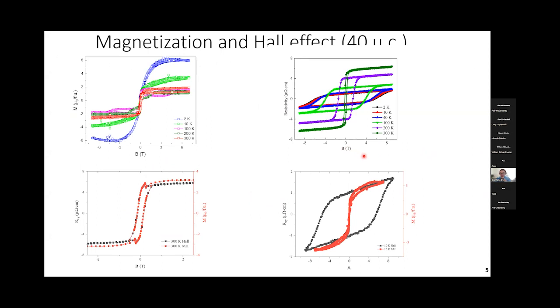So what is interesting in the film is the magnetic structure. When comparing with the single crystal, it implies a possible new order other than the ferromagnetic order, as in the single crystal. We use 2 ways to probe the magnetic structure. One is the magnetization loop, and the other is the anomalous Hall loop. The magnetization curve shows multiple magnetic transitions, like here, the shoulder in the loop, which may come from different magnetic sublattices formed by terbium and manganese atoms.